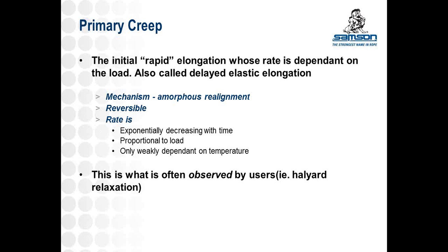So when you first load it up, over that first days to weeks, sometimes hours at a high enough temperature, what you see is those amorphous zones kind of straighten out and elongate. And this takes place, like I said, pretty quickly relative to the steady state creep, but it does quickly peter out. Important to note is this is often the quote-unquote creep that's observed by a user in the field. So if you were to take a piece of Amsteel Blue, using it as a halyard, and you were to tension that halyard, and a short while later it seemed to have slacked off or lost tension, people go, oh my God, it's creeping. And they expect that that rate of creep would continue. It will not. Basically, that portion of it might be a percentage of strain or a percentage of elongation before it stops growing and slows down and really hits that slow zone, which is orders of magnitude slower than this rapid part in the beginning.